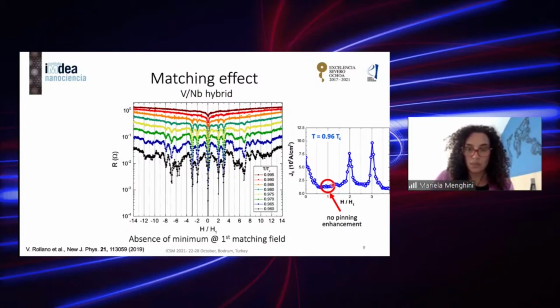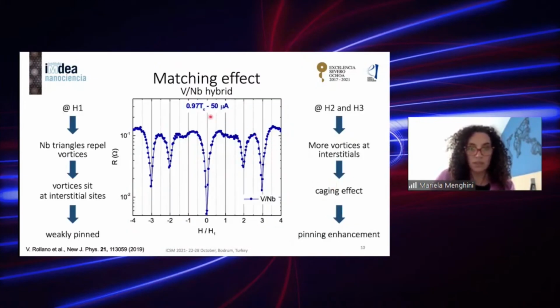So to understand this, we take one of those curves, this is 0.97 of Tc, and we look close to field equals 0. Our argument here is that at the first matching field, the niobium triangles that are already in the superconducting state repel vortices, so the vortices will sit at the interstitial sites between the triangles, and therefore this causes a weak pinning vortex lattice. Now, when we increase the magnetic field, so that we have the second or the third matching field, there will be more vortices at the interstitial sites, and this causes what is called the caging effect. So the vortices are again better pinned, and there is a pinning enhancement at these matching fields.